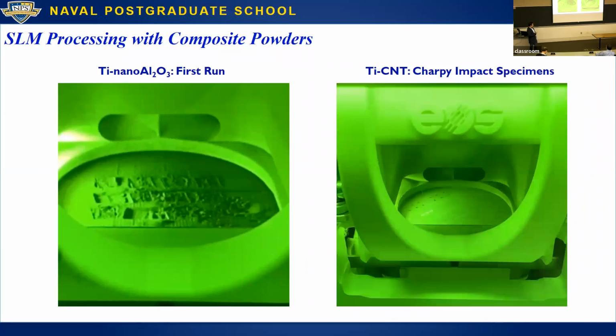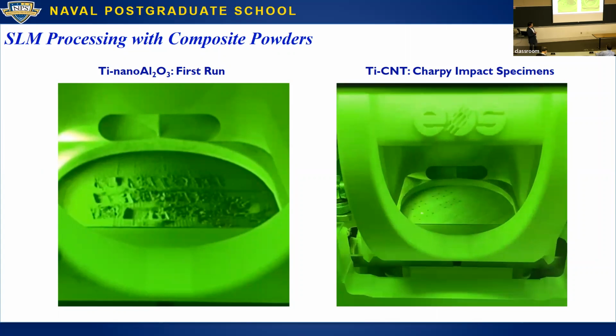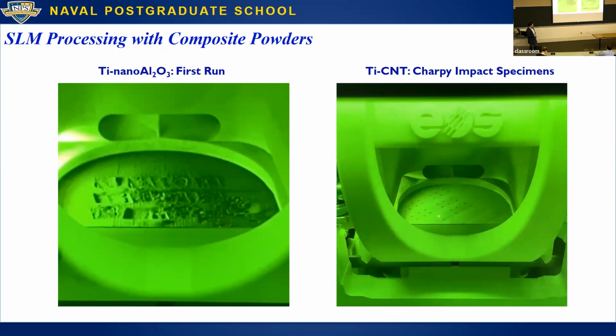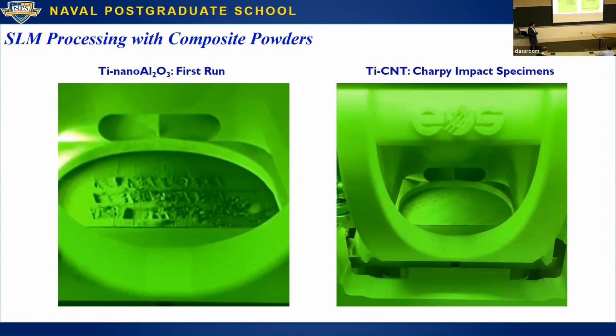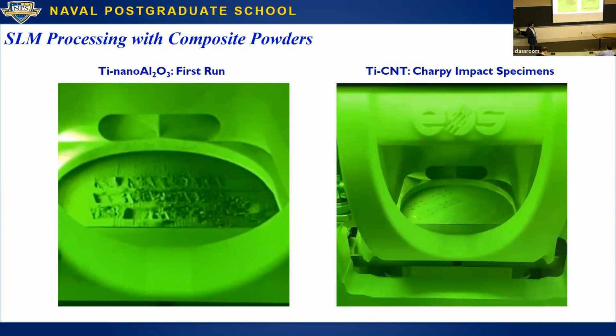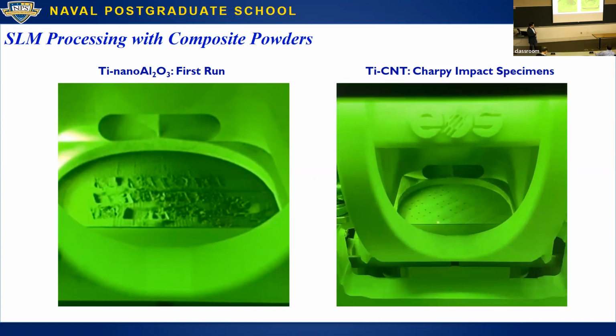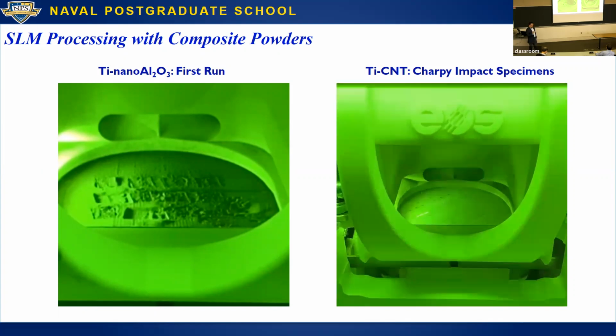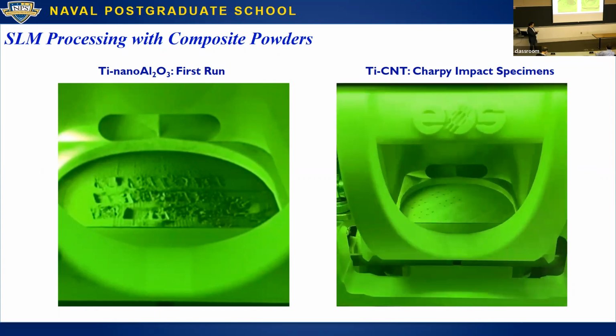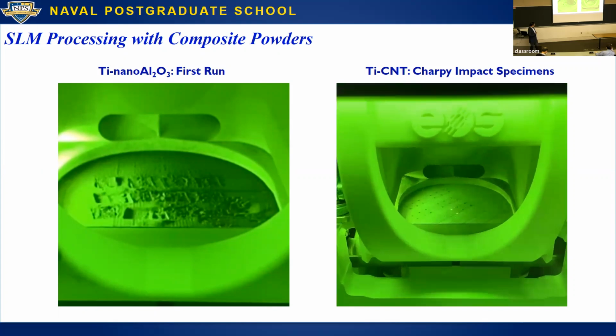And this is clearly what it's supposed to look like. This is essentially a single layer of powder. This is our titanium CNT. These are Charpy impact specimens that we printed. You see a uniform bed, and the laser is just printing, or essentially solidifying, the layer that you want. So it works very nicely in that case.